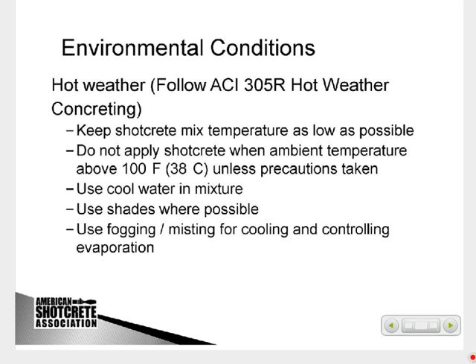Hot weather, it's similar to concrete. Once again, we have that exposed surface. So if it's 100 degrees or over, you have to have some special provisions with shotcrete. It may be fogging to help cool the surface to try to control early age plastic shrinkage cracking. We also like to keep the mix as cool as possible, so you may have cool water. If you're doing dry mix, you may have a tank where you can actually cool the water before it's introduced into the mix. If it's concrete delivered for wet mix, you can use the same hot weather provisions that you do for normal casting of concrete.